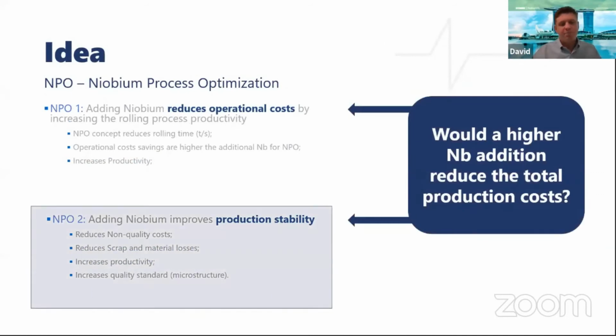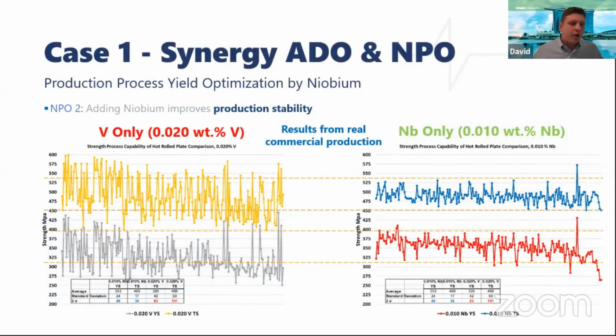Talking about the production stability and basically the synergy between ADO and NPO, these are really good examples of, let's say, side benefits that can come when you use both concepts at the same time. These graphics here, each single point of these graphics is a plate produced along 12 months in a company. And as you can see, on top, you can see the tensile strength, and the line underneath is the yield strength. The graphics on the left side is the vanadium only, with 0.02% vanadium added still. The graphics on the right side is the niobium only, produced with 100 ppm niobium addition. Both of them will have basically the same average for tensile strength and yield strength. But the variation is what makes the big difference here.